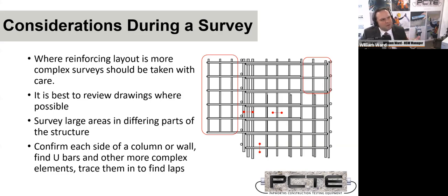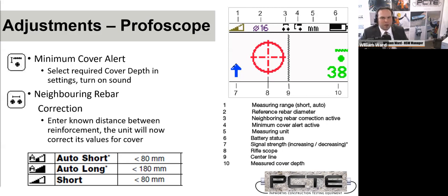If you think that it's going to be a source of interference or difficulty, or if you've experienced that maybe your cover values are slightly off because the diameters you're entering aren't quite matching up to your historical reinforcing bar, then it may be appropriate to destructively confirm a depth or use some mock-up pieces of the lower strength rebar, if you've got access to some, to come up with the very best settings for that kind of reinforcing steel, which is what I mean when you've got a complex job, you should use some physical evidence to set the machines up.